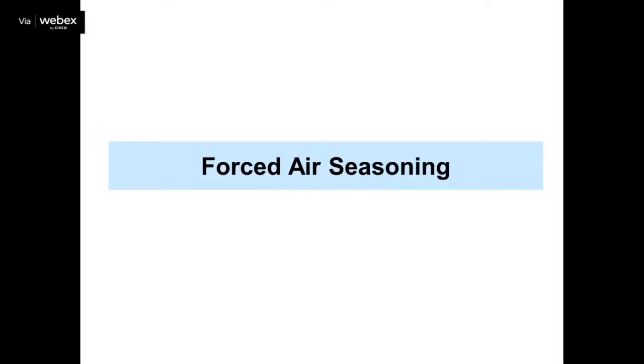The drawback of air seasoning is that we do not have any control over the natural conditions: the heat from the sun, the air which is circulated, the speed of the air, or the relative humidity. We do not have control over anything. So if we do not have the kiln, the air seasoning still takes around 3 to 4 months for properly drying a timber below FSP or the required equilibrium moisture content.